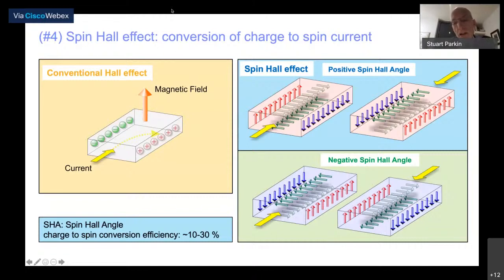An electrical current produces an accumulation of spin oriented in a chiral direction, clockwise or anti-clockwise, to that current direction. And so this means on the surface of this layer, we achieve an accumulation of electron spin. And that spin carries angular momentum, and that spin angular momentum now can diffuse into a neighboring magnetic layer, providing a torque on the magnetic moments in that neighboring layer. This is what it looks like.